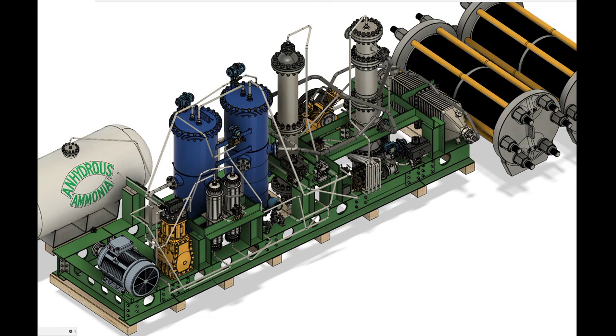The term packed bed reactors typically denotes the same thing as a fixed bed reactor. Most industrial catalytic reactors make use of these packed bed reactor configurations, including those that employ liquid reactant products. Depending on whether the reaction is exothermic or endothermic, in a fixed packed bed reactor, the catalyst will be inserted in a series of tubes fixed inside a larger mother container, which accommodates additional non-catalyst volume, permitting the flow of a coolant. In other cases, where heat is not a concern, the entire container itself may house the catalyst in totality. The former is typically employed in endothermic reactions where heat has to be provided, or highly exothermic reactions, where heat must be purged to prevent runaway temperature. The former case includes steam methane reforming, while the latter includes the World War II-era Fischer-Tropsch process.